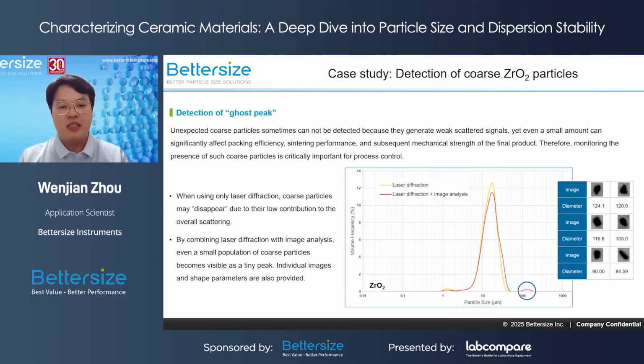If we only use laser diffraction, we get an orange curve, and everything looks normal, and there is no signal of abnormal coarse particles. But when we activate the combination test, something interesting happens. We can see there is a small ghost peak at around 120 micrometers. And when we check the individual images of the particles, we can notice that there are particles whose size is around 120 micrometers in the sample. This indicates the high sensitivity of the dynamic imaging system to coarse particles.